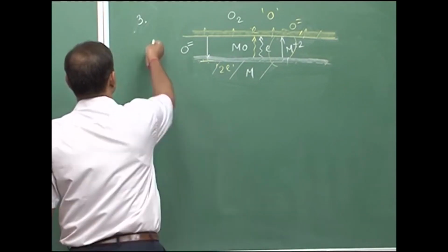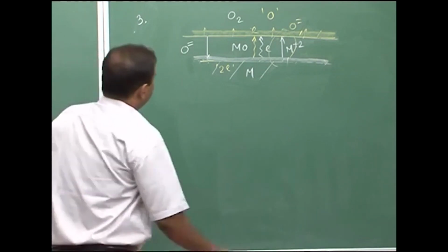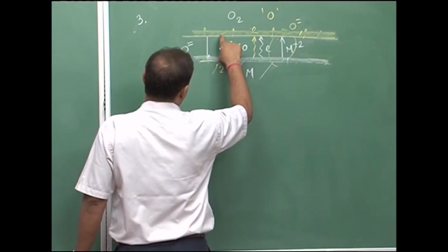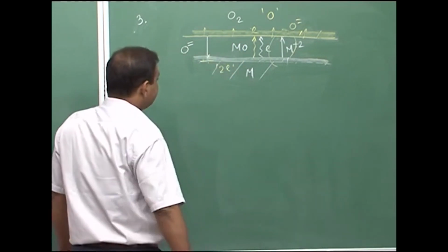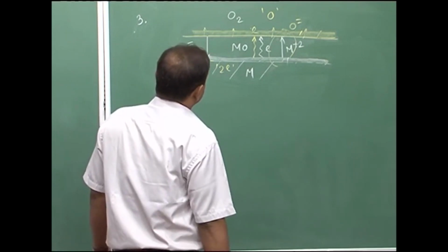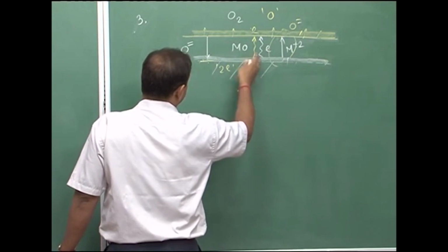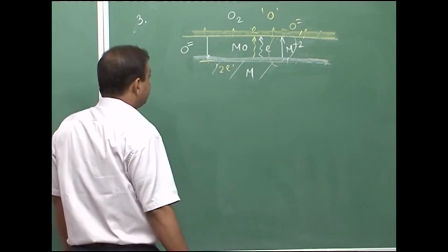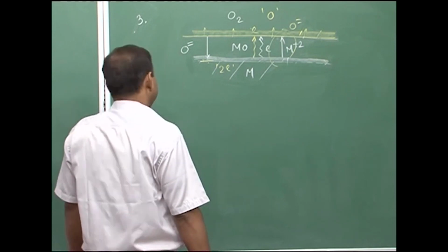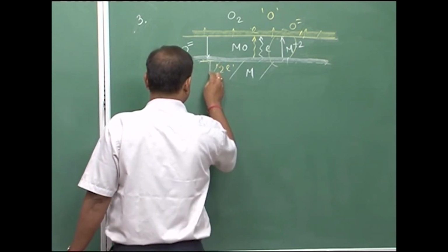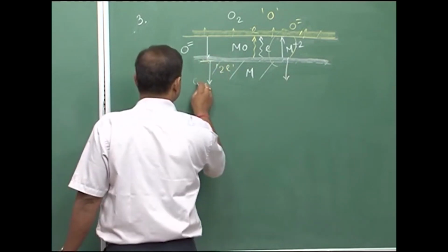Now, we were discussing stage 3, where we see that an oxide film is forming and growing gradually, and then we have oxygen and metal ion diffusion and the conduction of electrons. Those events are also happening. At the same time, there would be a continuing dissolution process.